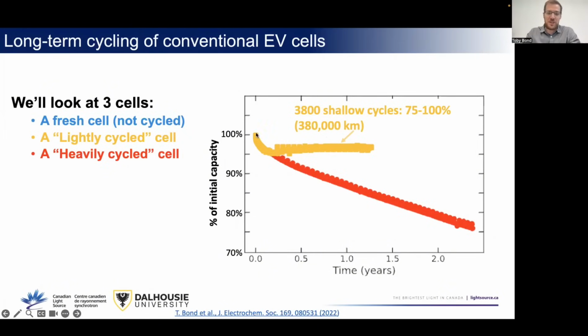So it's pretty good. You can see this initial dip in capacity that we often see because of that surface film that forms. But then it really flattens out. In fact, it looks almost totally flat here. And you can see what a difference this makes compared to this other cell in red, which I'm going to call the heavily cycled cell. This cell we cycled for longer, 2.5 years compared to more like 1.5 for this one.